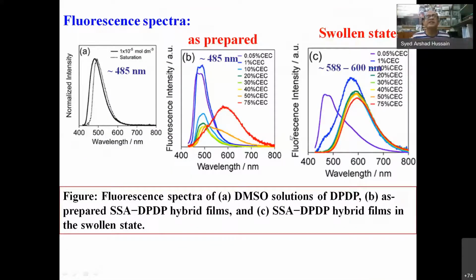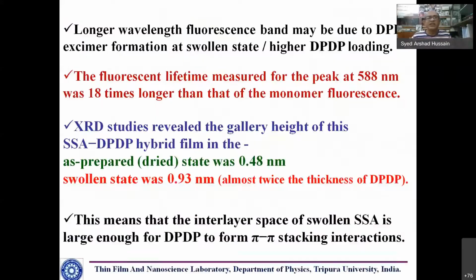Then we analyze why this happened. We measure the spectroscopy, absorption and fluorescence, and we see that during swelling, the fluorescence shows a longer wavelength, broad band, which is mainly some kind of specific aggregation related to excimer, that is pi stacking of one ground state molecule and one excited state molecule. Then we analyze further and measure the lifetime, and we have seen that the lifetime of this longer wavelength broad band is several times, 18 times, longer than the monomer fluorescence. And this is the characteristic of excimer formation.